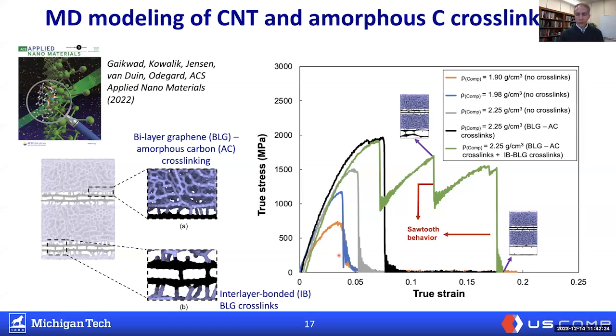We'll talk about each of these series individually. You see we have a couple of these: orange, blue, and the gray. This is what happens when we have no crosslinks. We do get a stress-strain response. It's maybe not as good as we would like. But now, if you take a look at this black line, what happens if we now put crosslinks between the amorphous carbon and the carbon nanotubes?